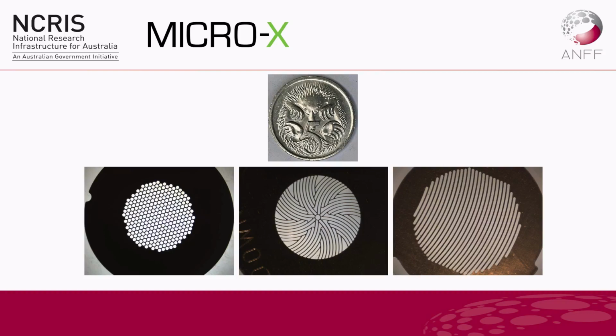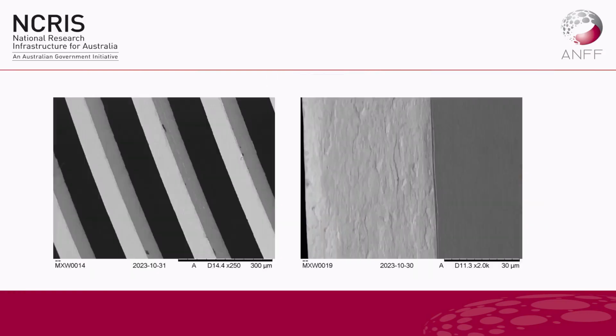It's not super fast. Some of these components still take about half an hour or so to etch out. But the results are really good, and it's very difficult to fathom doing it another way. Mark can tell you a little bit about the hours which were estimated. Yeah, so it was a bit of a nightmare job. But this is where the technology that I've hopefully introduced you today really shines, in these sort of components and difficult materials. Okay, it's an example of the sort of finish we get on there. Reasonable sort of edge finish, and it's actually quite good for a challenging material like tungsten.